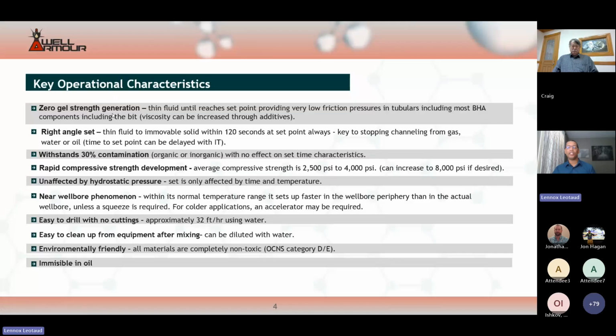And that is when it transitions from a liquid to a solid state. That transition, which we call a right angle set, always occurs within 120 seconds. By contrast, a cement system goes through a gel strength development phase when it transitions from a liquid to a solid material. And without having to provide too much detail, it is this static gel strength development property of cement that contributes to its inability at times to shut off gas or other types of flow in a wellbore. Well Armour has no gel strength development, and its transition time is always within 120 seconds.